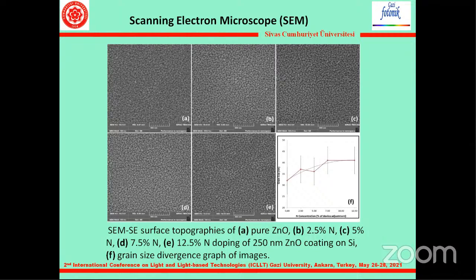Figure 2 shows scanning electron microscope secondary electron surface topographies O, A, B, C, D, E with different nitrogen percentages, doping of a 250 nanometer zinc oxide coating on silicon, and F, the grain size divergence graph of the images. As can be clearly seen from Figure 2, in all samples a spherical grain morphology was observed. This could be attributed to the formation of a good sputter regime and the energy within the substrate, and the zinc oxide accompanied by nitrogen doping. From A to E, with increasing nitrogen doping, a slight increase in grain size from 32 plus or minus 5 nanometers to 41 plus or minus 6 nanometers should be considered.